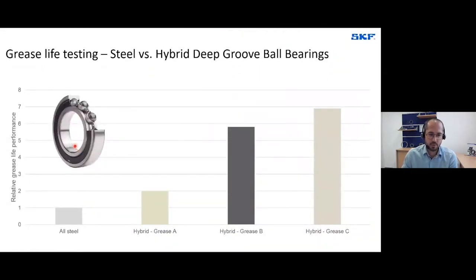And what has been observed is that the grease life with hybrid bearings is definitely twice as long as the one of steel bearings, which we have experienced with grease A. But the improvement with hybrid bearings can go up to way higher factors, like we have done one test where it went up to a factor of 7, and potentially it can go up even higher.